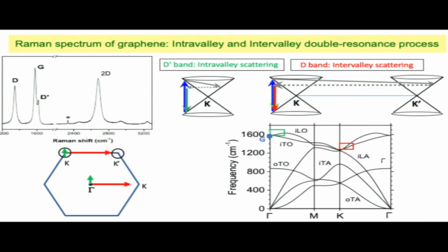It has to be a special kind of defect for that to happen, or can any defect do that? In principle, any defect can do that. But, for example, from the ratio between the intensity of this and that one, we can distinguish different kinds of defects. It can be point defects, it can be edges, any kind of defect gives rise to those peaks. But they have different cross-sections.